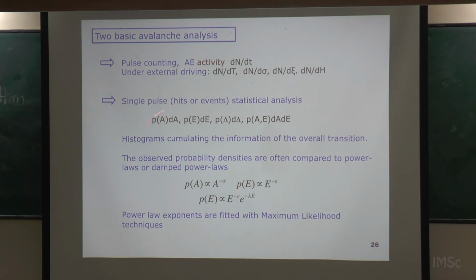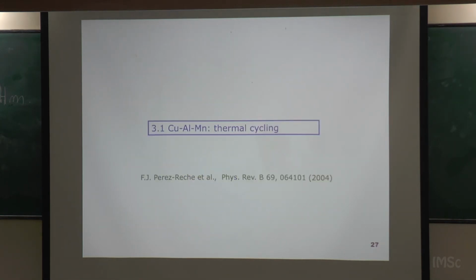And then with these curves, with this bad information, you have to check whether you have the power law or not. In some cases, as I told you, you find something which has an exponential correction, but there's a lot of statistical analysis here to fit this exponent, etc. And then also how we fit these values. There are different techniques. Some of them I explained on Monday, okay?